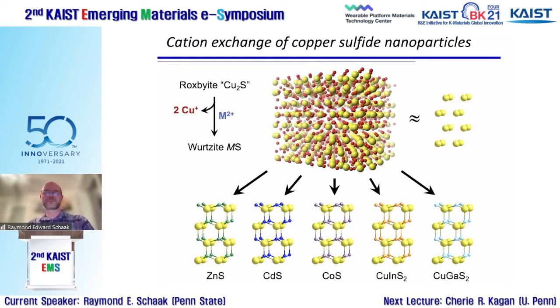But from a structural perspective, this is what our favorite copper sulfide crystal would look like. And we can simplify it. The yellow spheres here are the sulfur anions. That's the part of the structure that remains largely intact. And it's a pretty complex structure. It's distorted. It's got a lot of things going on. But you can simplify it to approximately a hexagonal close-packed anion sublattice. Those of you who are familiar with crystal structures, there's an ABAB stacking sequence of the sulfur anions.